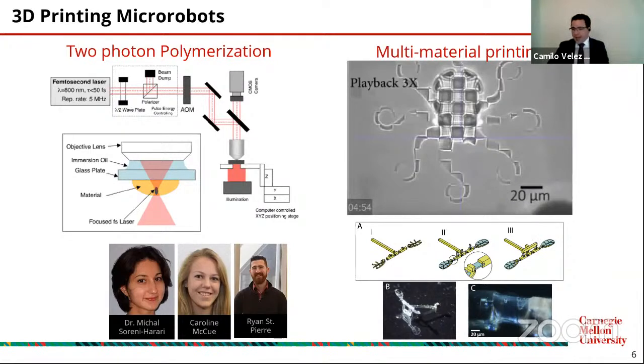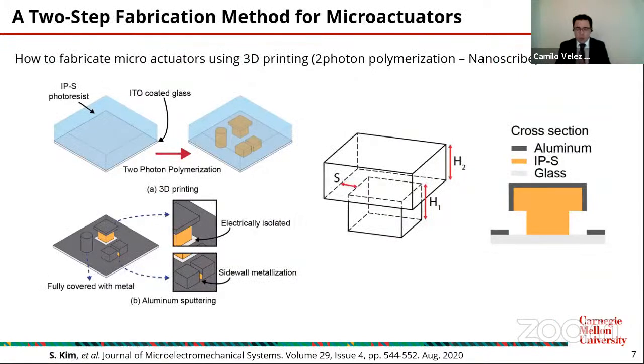So the first approach that we had, and this was work mainly conducted by Sukjun Kim in our group, was to start by 3D printing the material, and have the polymerization and the pieces in place. But we design the pieces in such a way that we can coat them or sputter them with a normal microfabrication technique, sputtering, with aluminum or a conductive material. And in designing or engineering the shapes, we are going to leave some gaps underneath the structures, such that we break the electrical conductance of the aluminum. So we are going to have areas that are conductive and non-conductive.